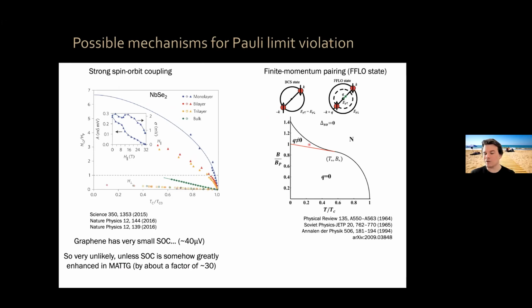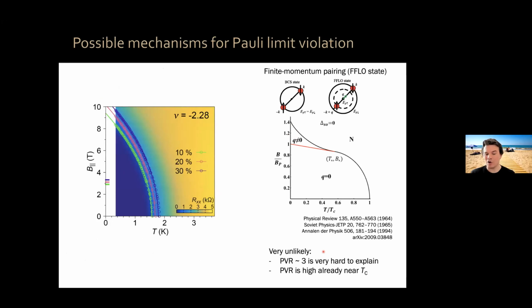Another possibility is FFLO states, finite momentum pairing states. Those can give you an enhancement of maybe 20, 40% at low temperatures, but we see enhancements of a factor of 3 and already starting from TC. So this again is not possible.